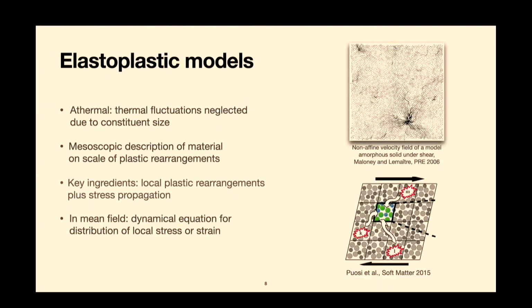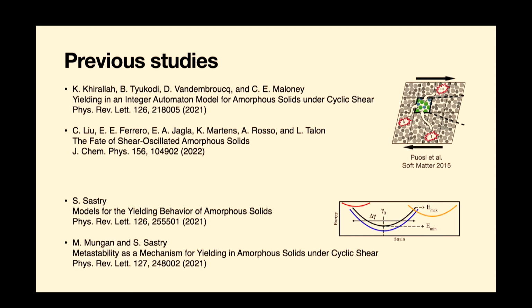You could build these models as spatial models, then you put them mostly on a grid. We're going to make this even simpler and generalize and do a sort of mean field version of this where we just throw away the spatial information and just look at the statistics of these blocks of the material. Okay? So it's called a mean field elastoplastic model. Okay. And there have been a number of studies of this model type already for systems under oscillatory strain. These are two papers where the lattice-based elastoplastic models were used, and they can, to a certain extent, replicate the experiments, but they're very hard to deal with analytically. You still have to run them numerically on a computer.